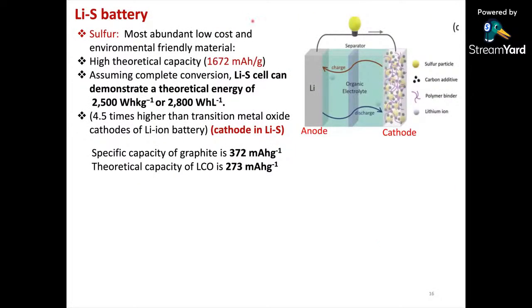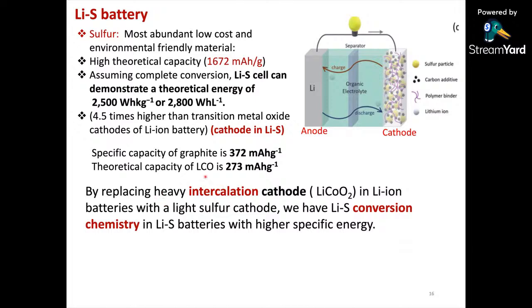We'll go to the lithium-sulfur battery, and all of us know that sulfur is the most abundant and low-cost material, with a capacity of 1,672 milliampere hour per gram. Assuming complete conversion of sulfur, it is possible to get an energy density of 2,500 watt hour per kg, which is 4.5 times more than that of the lithium-ion battery. Therefore, by replacing the lithium cobalt oxide cathode of the lithium-ion battery with a sulfur cathode, it is possible to have conversion chemistry instead of intercalation chemistry in the lithium-sulfur battery, with a higher specific capacity.